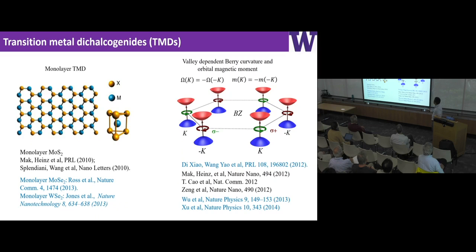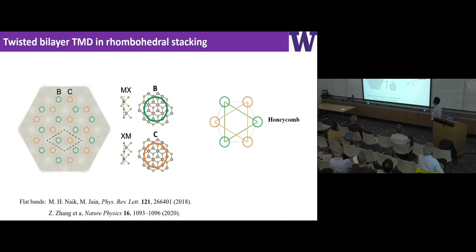So imagine we take one layer of this TMD and stack another on top of itself. Then we form a bilayer, but with a little twist. This is called a rhombohedral stacking moiré lattice. In this type of AA stacking structure, there are 2 energy-degenerate minima in the moiré lattice. We call them B and C. B is with metal on top of chalcogen, and C is chalcogen on top of metal. Then these 2 sublattices form a honeycomb lattice structure.